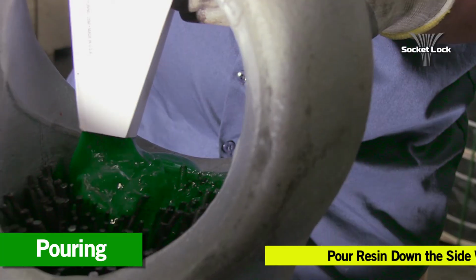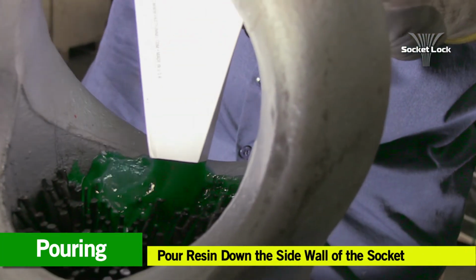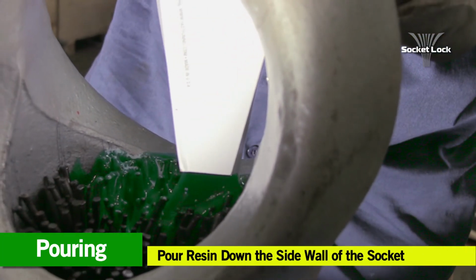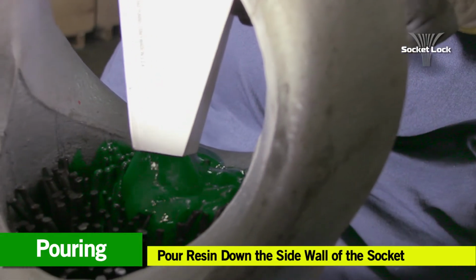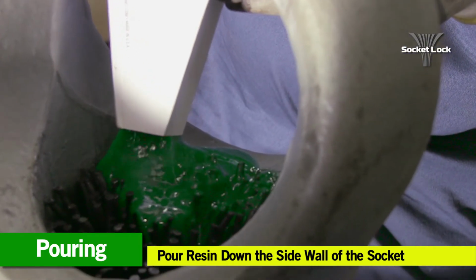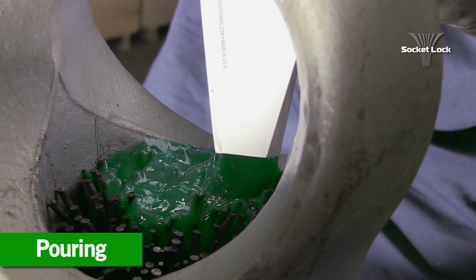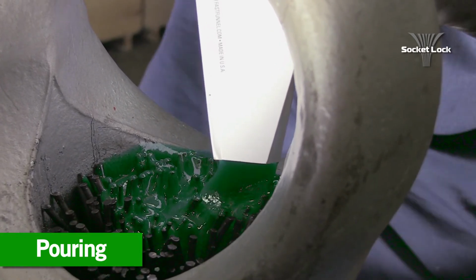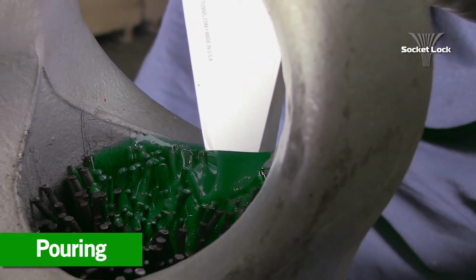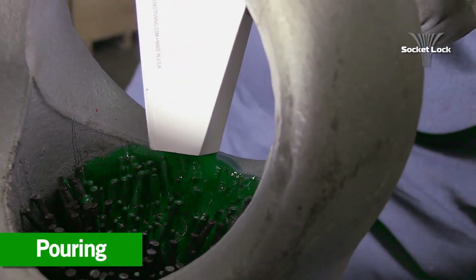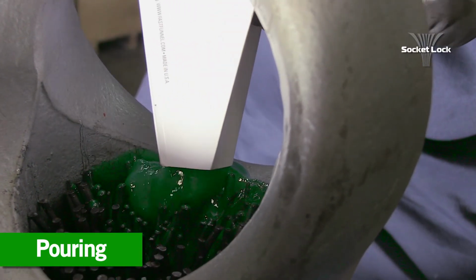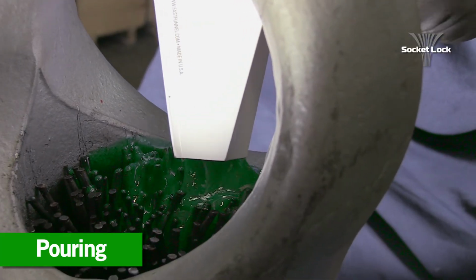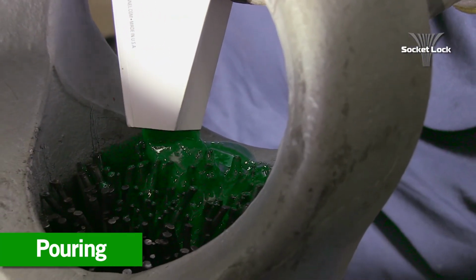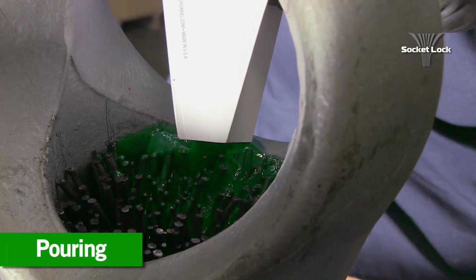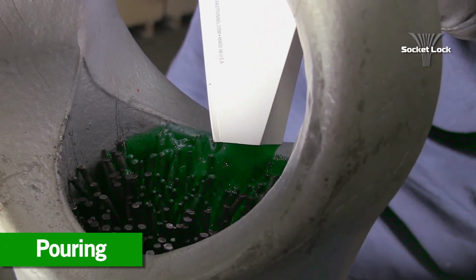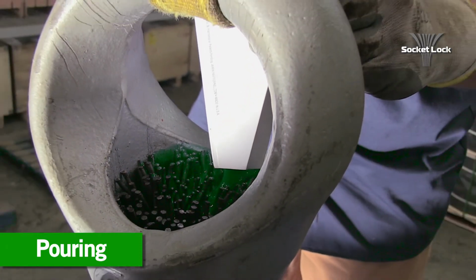Once mixed, position the funnel so that it will empty the resin down the side wall of the socket. This will ensure that air escapes and resin reaches the bottom of the socket bowl. Pouring down the middle of the socket could trap air and create a weak area of the cone. Pour the resin slowly and move the funnel from side to side along the edge of the socket bowl. The resin will tend to spread horizontally if poured too quickly, and this can trap air in the socket bowl.